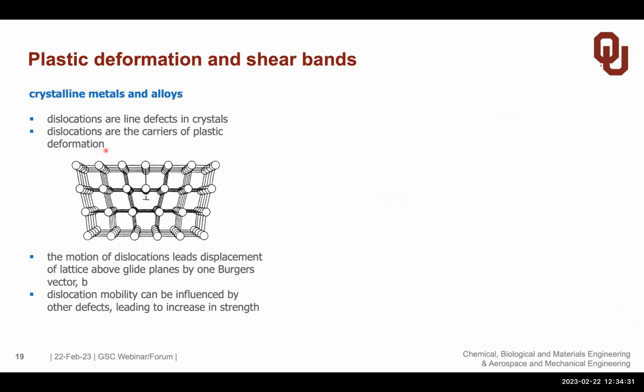So now, having talked a little bit about the structure of these metallic glasses, let's look at a property. If you take plastic deformation of a material and you go to a crystalline metal or an alloy, you have a defect which is a carrier of the plastic deformation. And this defect is called a dislocation, which is a line defect in a crystalline lattice. So it is very well understood how deformation of a crystalline material, single crystal or polycrystalline material, occurs via dislocation motion. And we also know very well how we can influence the dislocation motion and get, for example, higher strengths in the material by doping the material with impurities and preventing dislocations from moving.